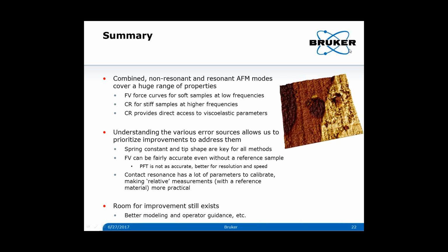So you can have a very hard sample where it might run down the tip, and you can use diamond probes to try and prevent your tip wear. But you can also have the opposite problem of the contamination. So I would say it's not necessarily the high frequency that's the problem. It's really the sample and then the load, how far you're pushing, and how much you're sampling. That's one of the reasons I mentioned in contact resonance, you may want to consider doing these point type measurements, which is how the fast force volume is doing it, as opposed to actually scanning, which might wear down the tip more.